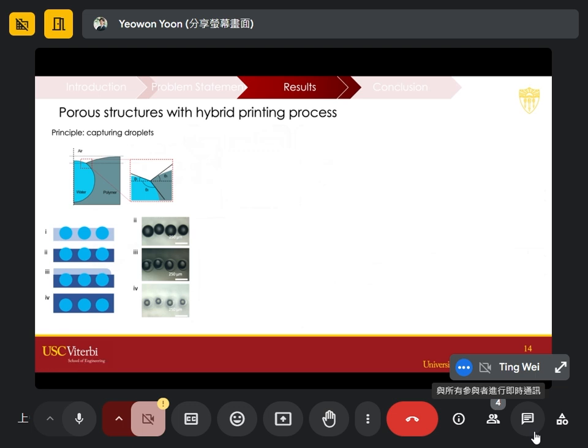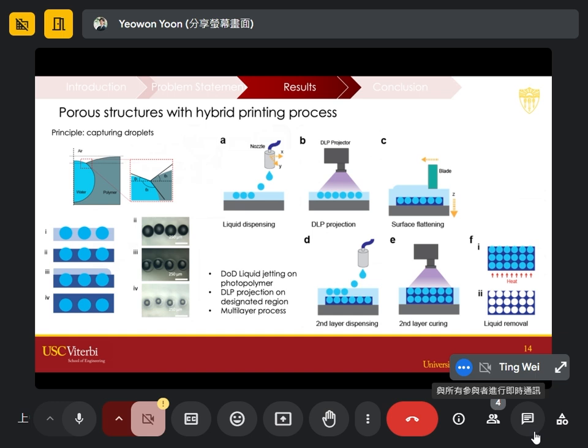Inspired by this work, we came up with this idea of 3D printing of the porous structure. It goes from A to F process. We dispense a liquid, which is DI water in this case, and then we capture it using a DLP projector. So every layer is solidified, including the surrounding water. Then this one goes down, another resin layer comes up, and we dispense more droplets and cure it. This goes on to print a structure where multiple water droplets are located inside. Once it's done, we take the sample out from the substrate and heat it, and the water will evaporate. All that remains is the structure with the pores inside. So we can 3D print a porous structure, a porosity embedded structure, using this process.